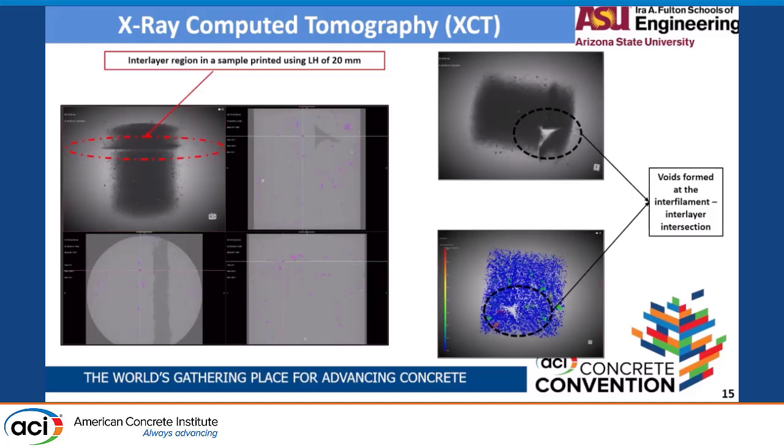It is the void that forms a continuous channel through the specimen, and which was responsible for the enhanced transport of ionic species in the NSSM test also. Similar was observed for 13 mm also, but in 6 mm, because of the higher pressure, the voids were not as significant.